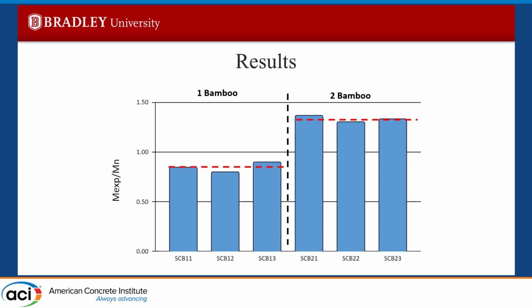And this could be due to the fact that when you make the sulfur concrete, you have to pour it into the specimen. So as you increase the bamboo, there's more area for the sulfur concrete to bind to. So as you add more bamboo, it creates a stronger, tighter bond to the bamboo itself. So that's why we're seeing an increase in this.